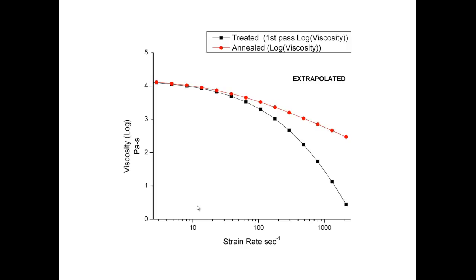For instance, here this is a polycarbonate melt, and the black curve is a disc which has been molded from the pellets that were collected at the end of the double rheofluidizing treatment, and we compare that with a virgin, which is also the same curve as the red curve, obtained by letting the melt rest at the rheometer at the high temperature, so that if it is in non-equilibrium, then we hope to re-establish an equilibrium.